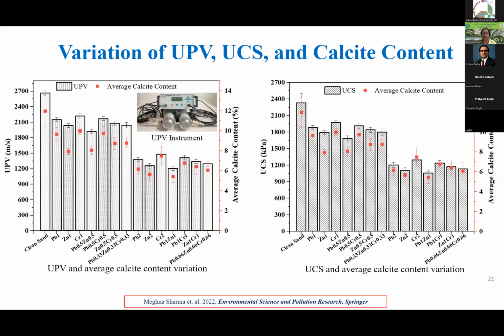And then ultrasonic pulse velocity and unconfined compressive strength of soil and calcite content. These things were compared and analyzed. So in the clean sand where no contamination was there, the UPV was more than 2400, and the other contaminated samples, these are 1000 mg per kg contaminated samples, also have more than 1800 meters per second UPV. And the effect of contamination can be seen more in the 2000 mg per kg sample, and zinc was found quite toxic here also. So that's why the calcite precipitation got reduced.